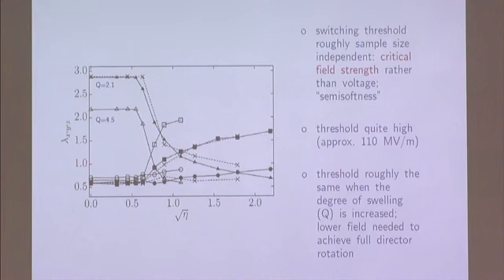Now, okay, we have this threshold. One can also estimate the magnitude of the field strength corresponding to this threshold. It turns out to be actually quite high. So this resistance to rotation, in our case, is still rather high, and so the existence of the threshold somehow suggests that we are dealing with semi-soft systems.